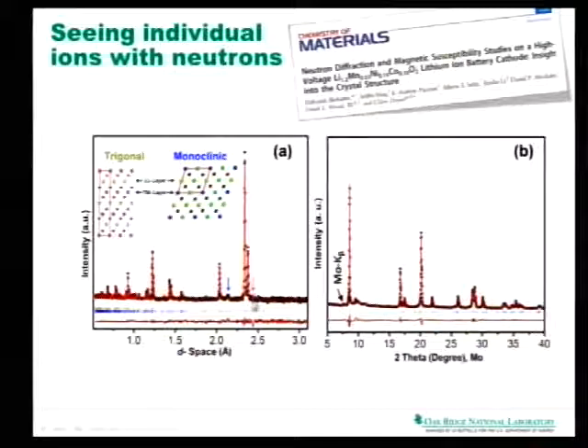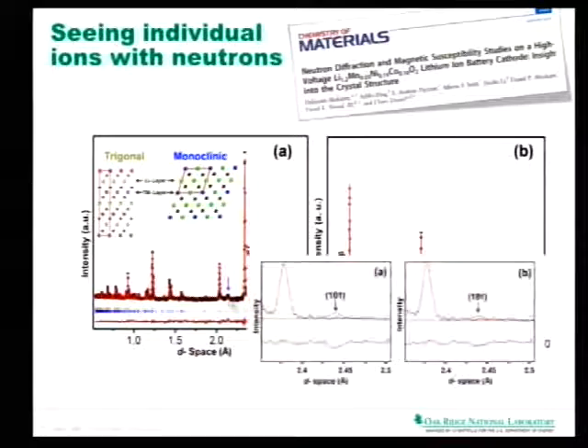There are some peaks which don't fit. And that shows the power of neutrons in there. If you zoom in and you look at that peak, if you just take the regular crystal structure, you put it in, you generate a peak where there is no peak in your real data. So here now you can start fiddling around with your structure.